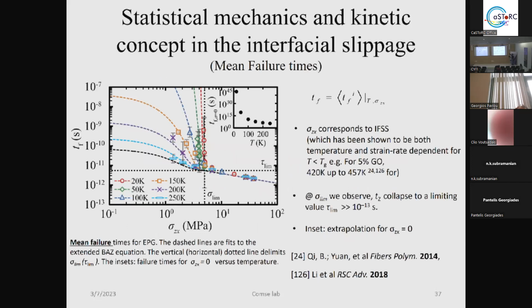Here you can see the plot of the failure times versus the shear stresses that we put in order to pull out the system. And the first thing that someone can observe is that in the right regime of the plot, we have an exponential behavior of the system. And also we have a dependence on temperature, with different colors at different temperatures. All this behavior holds up to the sigma lim, which one can see with this axis here. And after that, the phenomenon changes and becomes log-linear. And it becomes temperature independent. All the colors are on the same line, and we have a straight line and not exponential. This also is a different picture from what Zhurkov saw. So we see another disagreement, not exactly disagreement, but another view of the system.